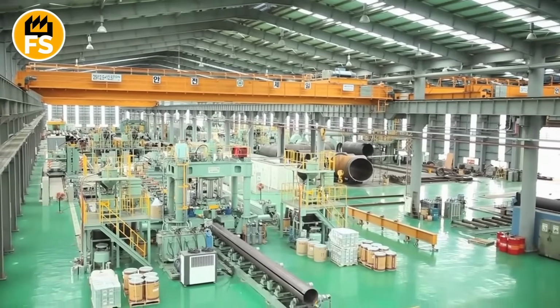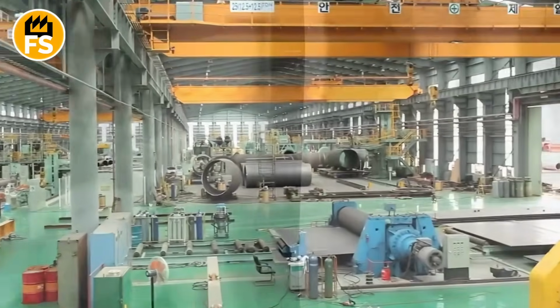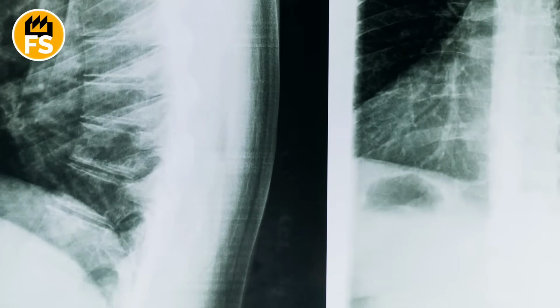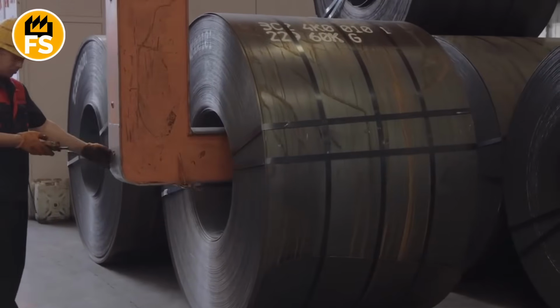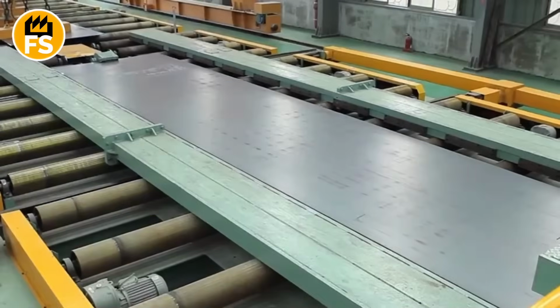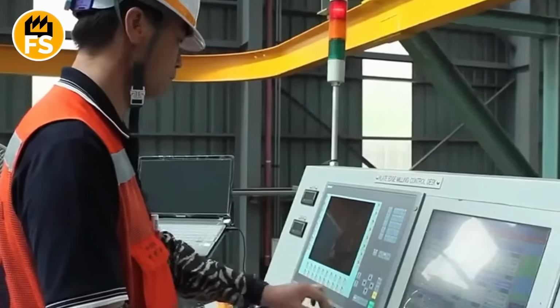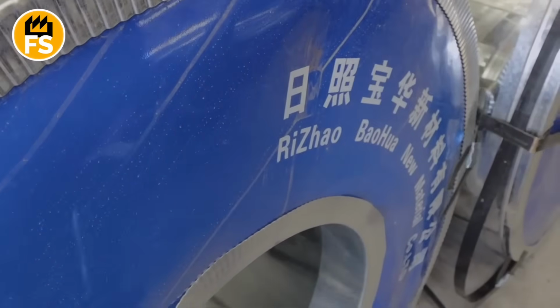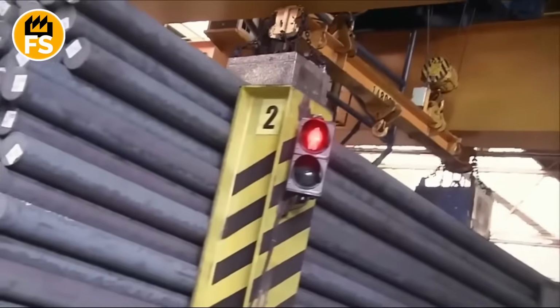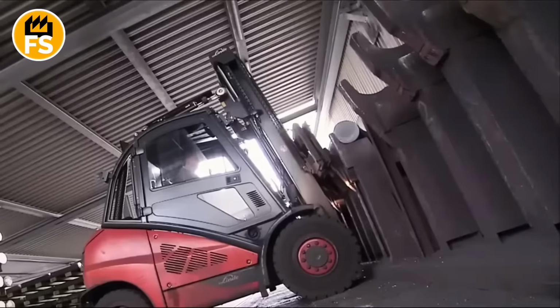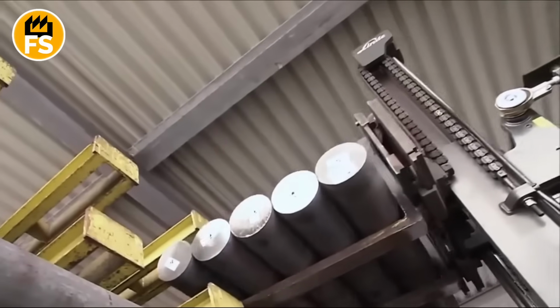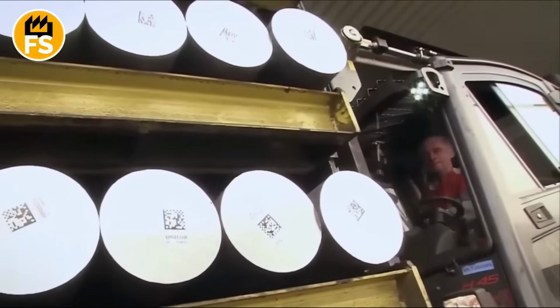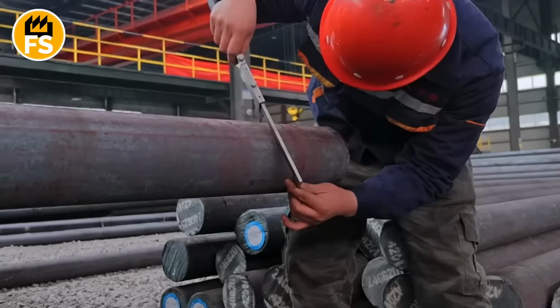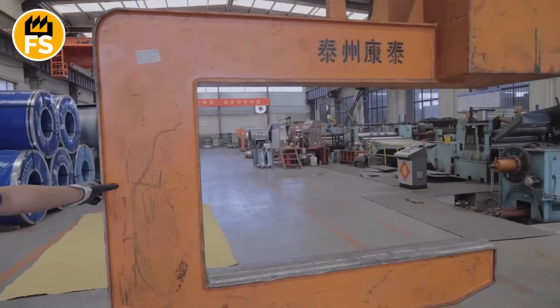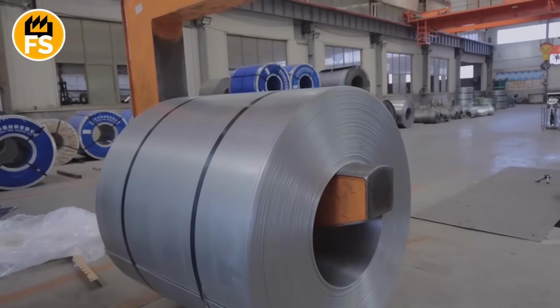Defects shall not pass. First, the billets get an X-ray. Well, not exactly X-ray, but something similar for metal: ultrasonic testing. You heard that right. The billet is coated with a conductive gel, like for a human ultrasound, and a transducer is moved across it. Special transducers shoot sound waves at a frequency of 5 megahertz. That's 100 times higher than submarine sonar. This is how they search for cracks and inclusions of foreign materials within the billets. The system builds a 3D map of defects with an accuracy of 1/100th of an inch. If it finds a saboteur, the billet is marked with red paint and sent to metal hell for remelting.